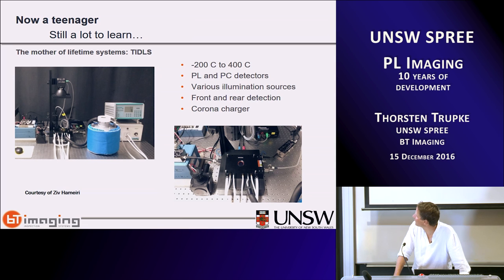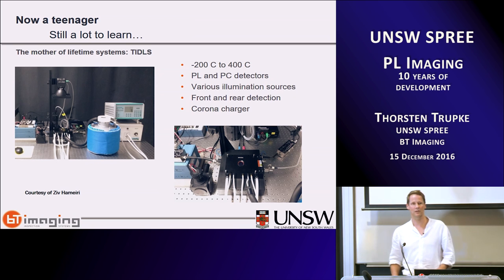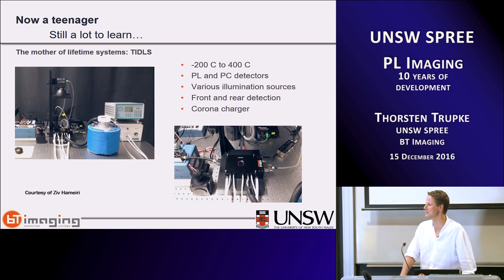So let's talk about the measurement systems that Ziv has set up. Ziv has built this beautiful system in LG25, which is a temperature-dependent QSSPC and QSSPL measurement system. So you can really think of it as the mother of all lifetime systems. It covers a very wide temperature range from minus 200 to 400 degrees C. It has PL and PC. We can switch between different illumination sources, LEDs, lasers, flash, and what have you.